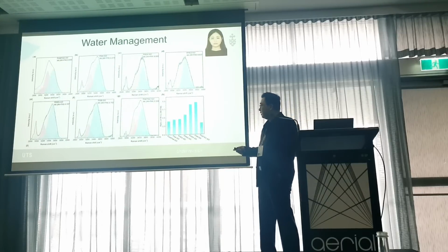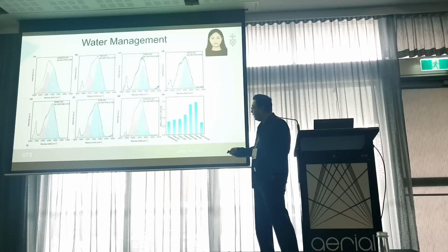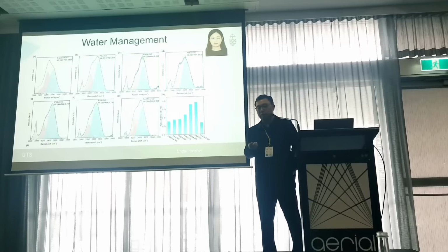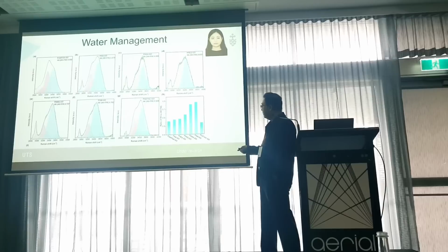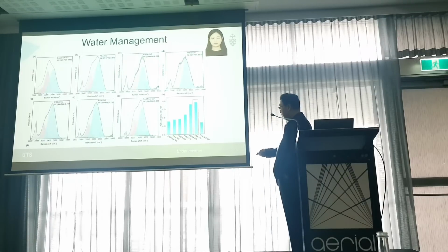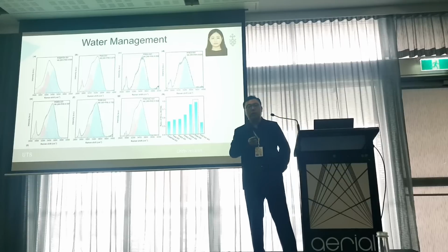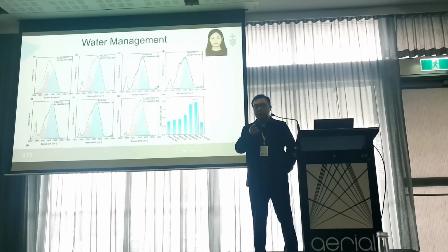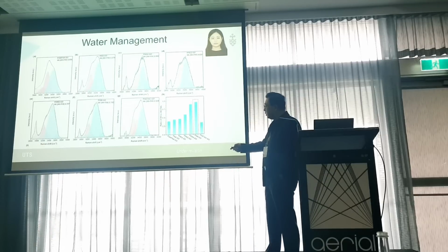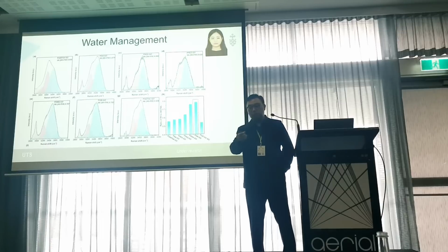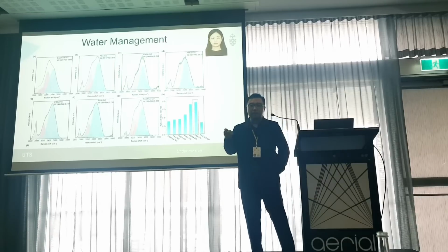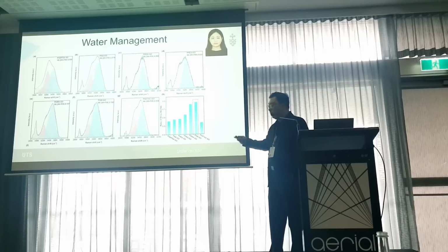So interesting is that we find that for this hydrogel PN, with the amine group as a functional group, they show a higher intermediate water content. And these results are summarized in this figure. As you can see, PN hydrogels have the highest intermediate water content. And intermediate water is believed to be at a slightly excited state. That means the evaporation enthalpy of intermediate water is lower than the free water. So if we have a higher intermediate water content, in this case about 78%, 78% of the water inside the hydrogel is intermediate water, activated by the polymers, by the hydrogel itself. So therefore, under solar illumination, it can generate fast water evaporation.